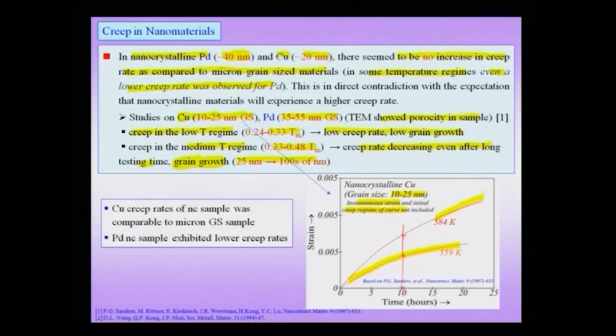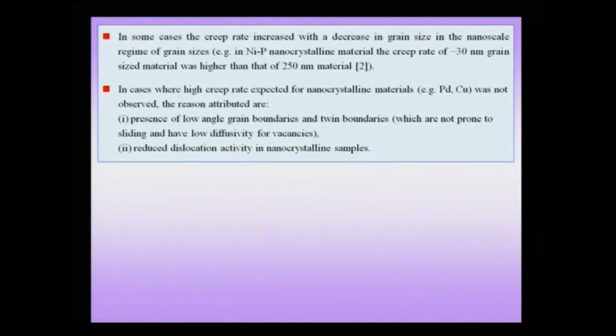To summarize this slide, in copper the creep rates in the nanocrystalline sample was comparable to the micron sized grain size sample, but in palladium nanocrystalline sample, actually we could see certain lowered creep rate at certain temperature regimes. So, this was extremely surprising, as in the case of creep of nanomaterials. But this is, of course, as I pointed out, in the case of testing of nanocrystalline materials, even in cases where we are able to control the artifacts, artifacts include porosity in the initial sample, artifacts include grain growth, which we just talked about. Even when we are able to account for some of these effects, there is no universality.